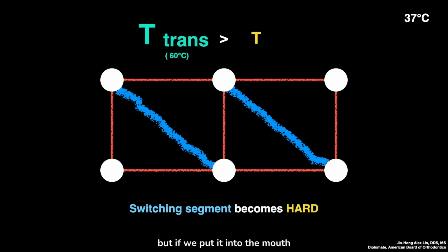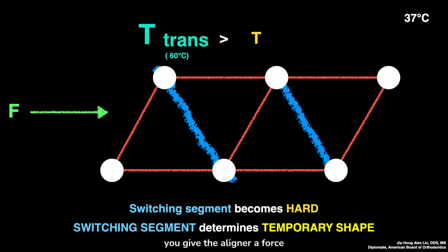But if we put the aligner into the mouth, which has a temperature of about 37 degrees, and below the TG of the switching segments, because we're at a lower temperature, the switching segment cools down and hardens. Now we did not change the shape of the aligner, but now it's the switching segment instead of the hard segment that's holding the shape of the aligner. So now inside the mouth, you give the aligner a force. It could be from mastication, it could be resistance from the tooth, but eventually the aligner will gradually lose its elasticity and deform after wearing.